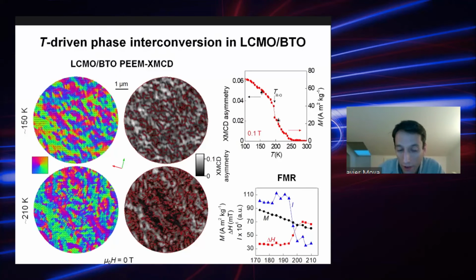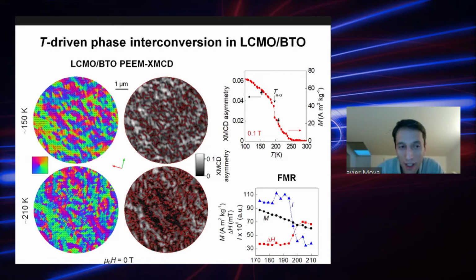And indeed, for the calcium manganite, we did this study a few years ago, where we looked at this phase transition with a number of techniques. So this slide summarizes all the techniques that we used. On the left, these are magnetic images done by PEEM with X-ray MCD contrast, which we run on the synchrotron here in the UK. If you concentrate on the two images in the middle, you can see that when you go from the high temperature phase to the low temperature phase, you have an increase in the amount of ferromagnetic phase. Here the paramagnetic phase is black and the ferromagnetic phase is white.